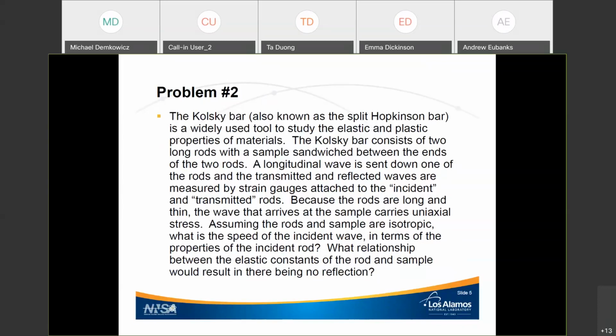So even though there's lateral strain, and therefore one can think of a volume strain, one could write down a somewhat more complicated expression involving volume strain, but the wave itself can be described strictly in terms of acceleration and the displacement along the same vector direction as the acceleration. So the stress being sigma 1,1, we can treat that acceleration as strictly along the x direction.